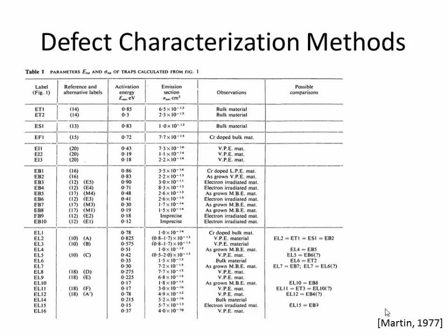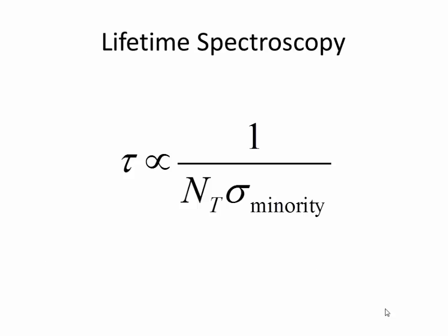You can do a comparable measurement by actually looking at the lifetime itself. If you measure the lifetime by photoluminescence decay or photoconductance decay, and look at how it depends on, say, temperature and injection level, you can extract information about the defects from it. It's nice because you only get information about the lifetime limiting defect. I mean, it's a limitation, but it's also a nice limitation, because you only get information about the specific defect that's limiting your efficiency.